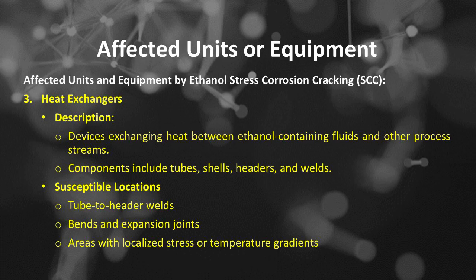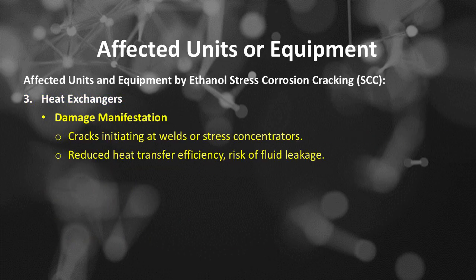Affected units and equipment by ethanol stress corrosion cracking. Number 3 is heat exchangers, includes devices exchanging heat between ethanol-containing fluids and other process streams. Components include tubes, shells, headers, and welds. Heat exchangers. Susceptible locations include tube-to-header welds, bends and expansion joints, areas with localized stress or temperature gradients. Heat exchangers damage manifestation includes cracks initiating at welds or stress concentrators, reduced heat transfer efficiency, risk of fluid leakage.